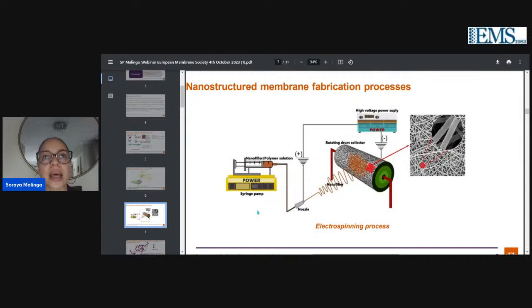We've also explored another fabrication process, which was taken from a study by Diallo, I think in the early 2000s, where we have attached a commercial membrane on a rotating drum. So we are not just spinning fibers on a foil like you would traditionally prepare nanofibers, preparing mats. But in this case, we have a commercial membrane rotating on the drum collector, and we prepare the nanofiller and the polymer solution, which is inserted in the syringe, and we electrospin on the commercial membrane.